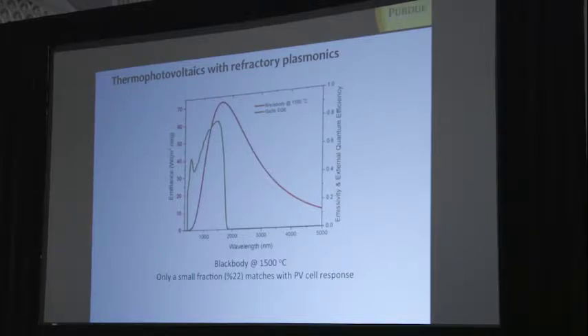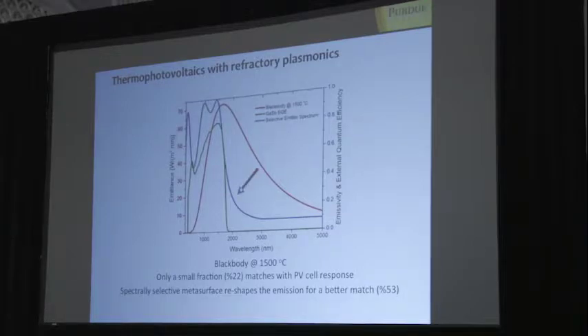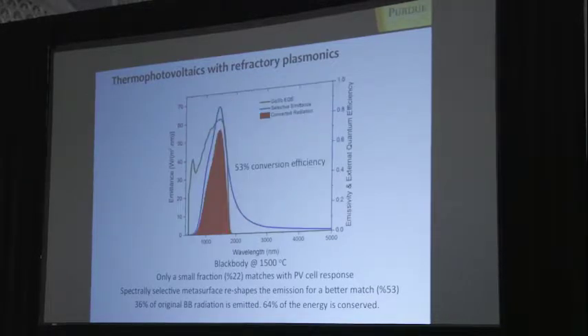However, if you put this frequency selective emitter, that's what happens. Now it matches very well the area where this conversion of energy into electricity is really high. And in this case, basically, you get the efficiency, which is 53%. It's just appreciate, it's a very simple structure, like 50 nanometer simple structure, which makes this frequency selective emitter. And of course, there is no new idea here.